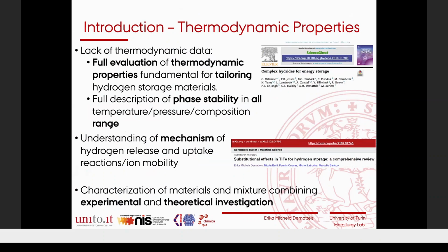In our research, we are also focusing on the characterization of these materials from the thermodynamic point of view. This is because in the literature, there's still a lack of thermodynamic data on these compounds, and there's a need for a full evaluation of thermodynamic properties and also to better understand the mechanism of hydrogen release and uptake, and also phase stability in all temperature, pressure, and composition ranges. In order to tailor these materials from a compositional point of view, or also by mixing them, and enhancing kinetics and reducing the thermodynamic barrier of hydrogen release.